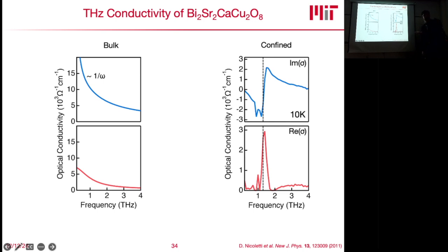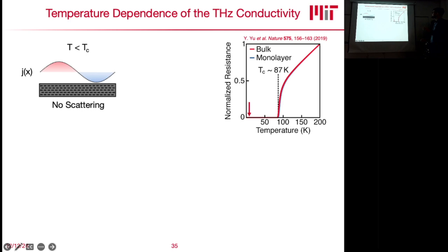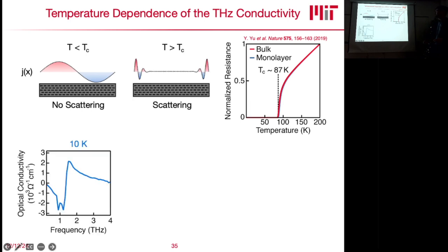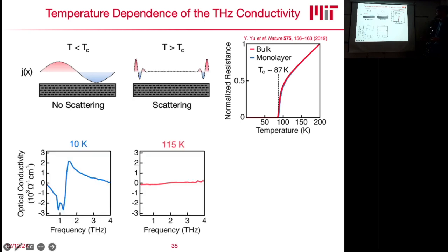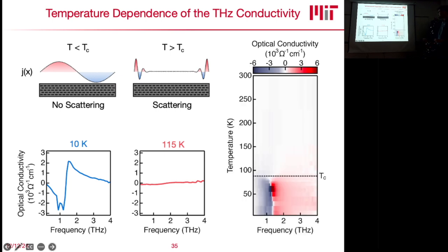And this is already the first demonstration that the confined electrodynamics of these samples are very different. Yes? Oh, okay. Yeah, and then of course we can do a temperature dependence of all of this. And what we find if we go from below to above TC is a stark contrast, so we lose all of these confinement effects. And if you take the full temperature dependence of the imaginary conductivity, you find this very nice transition perfectly at TC. So you go from a geometry-dominated regime to a scattering-dominated regime, and we can follow all of this.